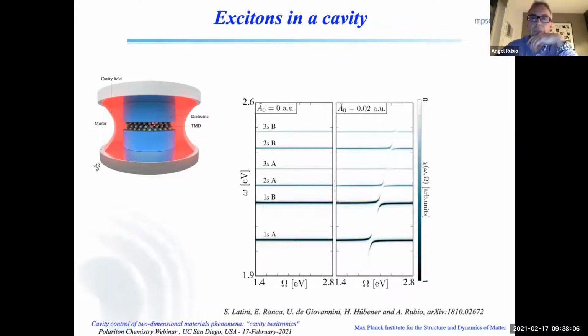Then what we do is we put this material in a cavity in which we embed it with highly insulating polymer media in order to have the frequency of the cavity, which is the length of the cavity, tune. And then I am going to show you what is the energy spectrum as a function of the cavity frequency, in this case, the length of the cavity.